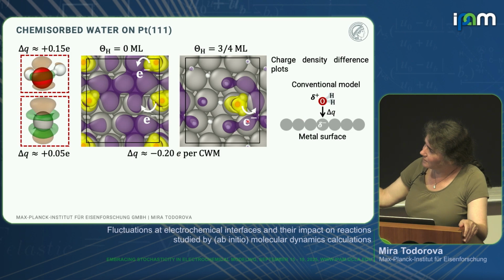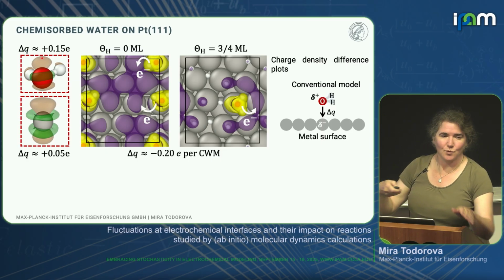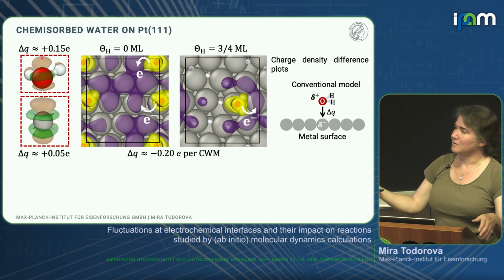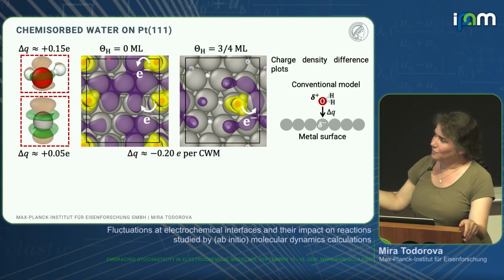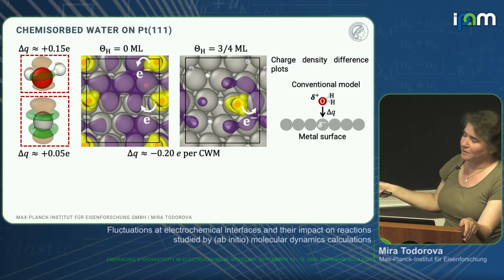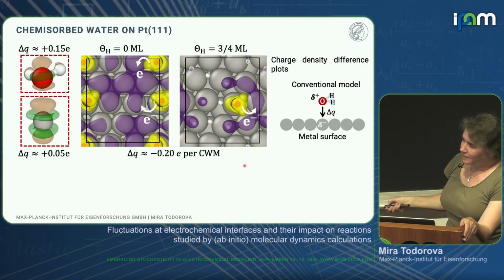If you look here at the top view, now this is the water molecule, this is adsorbed on platinum, and it seems that this platinum-water complex that is formed, so it's like a molecular bond because both the platinum and the water seem to donate electrons to the surface, and they're donating it to the surrounding platinum atoms. So it is really, when we do the math, then kind of they really counteract.